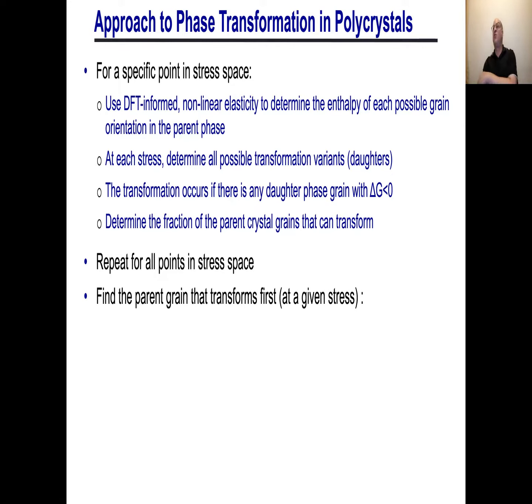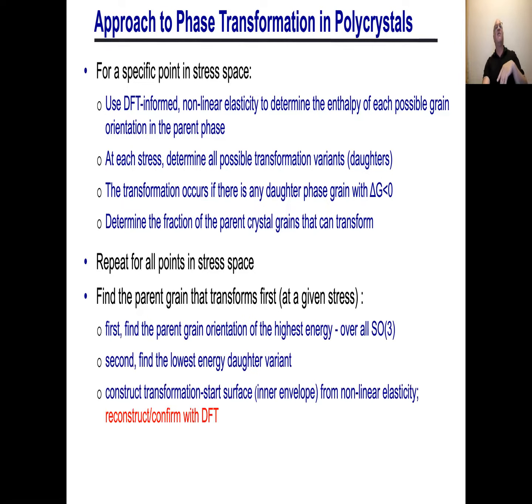And if I want to find the minimum stress I can apply in order to get the phase transformation, all I do is find the parent grain orientation that has the highest energy. I keep increasing the stress along that radius vector in the deviatoric plane, and we look over all possible grain orientations, SO(3), and find the lowest energy daughter variant. And from that, in that particular stress path, I can find out what the minimum stress is for the transformation to begin. Once I have that from this DFT-informed nonlinear elasticity, I can go back and verify this with density functional theory along that whole transformation surface. Okay, so data.